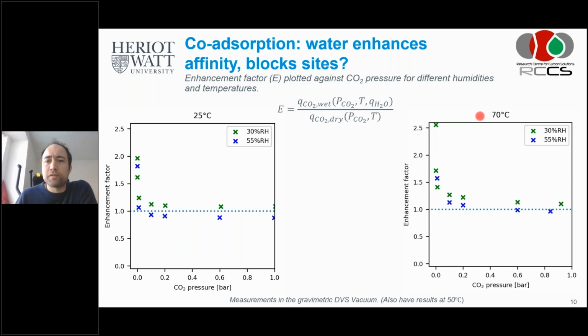Now we've done exactly the same for 70 degrees. We also have it for 50 degrees, but the trend is very much the same. A question that we have is, you see that the blue line even goes a little bit below the parity point. So no additional uptake in the presence of humidity, and it seems to suggest that there may actually be a little bit less uptake in the presence of humidity, which may be caused, for instance, by site blocking or by limited access to the amino groups. But this needs to be confirmed on many more materials. We need much more of this work on a range of different amine functionalized sorbents.